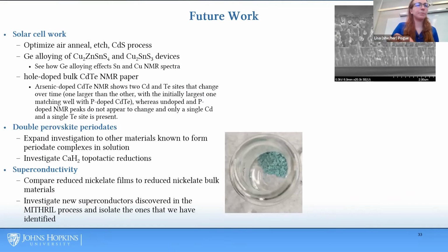So for future work, for the solar cell work, there's more work to be done in optimizing the air anneal and etch process and the growth of the cadmium sulfide buffer layer. There's also work going on in germanium alloying of CZTS and CTS devices. This is to introduce back surface fields and engineer the band gap near the buffer layer, absorber layer interface to improve performance.